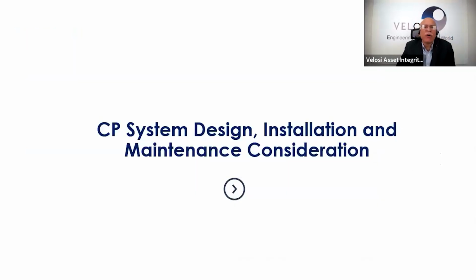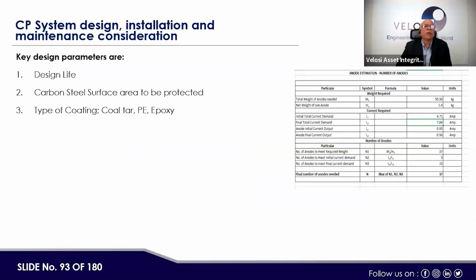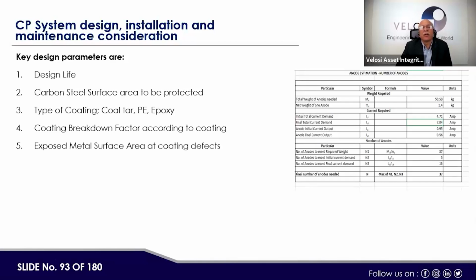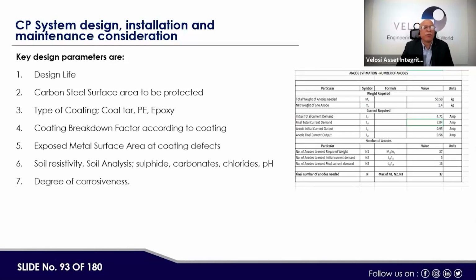So here, when we have CP system design, installation, and maintenance considerations, we take one example: the design life of the asset, a carbon steel pipeline, the surface to be protected, and the type of coating, coal tar or epoxy. Then the coating breakdown factor according to the coating we need to understand. Then the exposed metal surface area at coating defects. Then soil resistivity and soil analysis: sulfides, carbonates, chlorides, and pH. Important: the degree of corrosiveness we have to see externally. Electrical isolation, foreign structures like earthing, and pipeline crossings we need to consider.